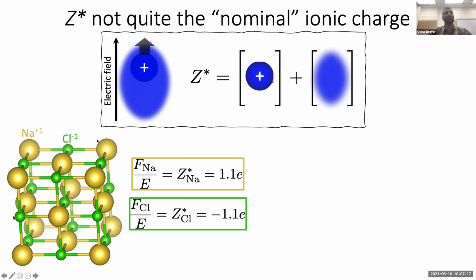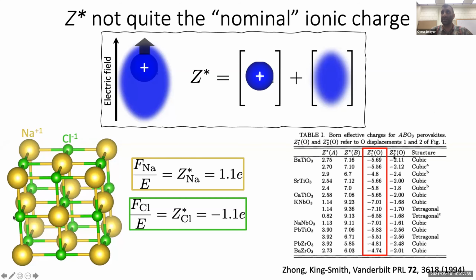And we can see this if we take, for example, a very ionic material like sodium chloride, and we calculate or measure the Born effective charges, we get something that's a little bit different from the formal ionic charges that we might expect. And then, of course, in the materials that are near and dear to many in the audience, the ABO3 perovskites, we've known for a long time that the Born effective charges on these materials are anomalous. For example, if we look at oxygen, a specific equatorial or apical oxygen sublattice, we see that the Born effective charges are very different than the -2 nominal ionic charge we would expect for oxygen. And this has a lot of effects on the properties.